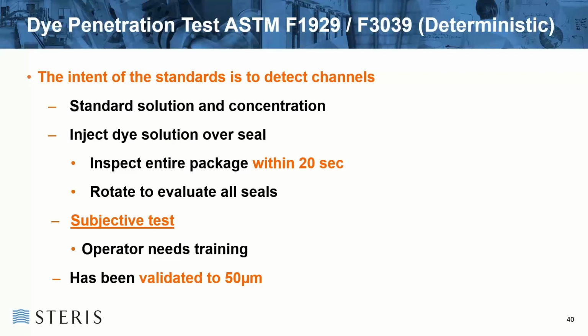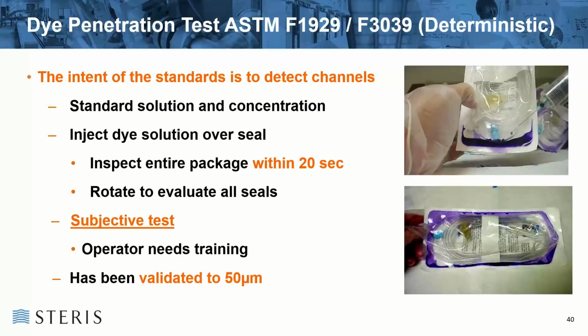In relation to F3039, it's normally used for the likes of foil and foil pouches, and there are 2 test methods in there, one for the seals and one for the surface, and both are deterministic type tests. The problem is that they're subjective, and the operator needs a lot of training to see and know what exactly they're looking at, and is it a failure or is it not a failure? And I'll show you why in a minute. But the advantage of this is that it's been validated down as far as 50 micron.